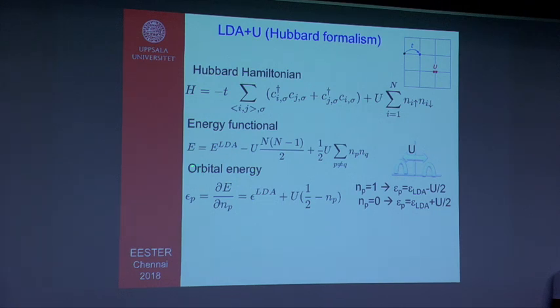And if you calculate the orbital energy, which is the derivative of the total energy with respect to the orbital occupation, you will see that it looks like this. It directly comes from here. Now if you put n, this occupation, equal to 1, then you see that the orbital energy comes out as epsilon LDA minus U over 2. And if you put it 0 in this expression, it comes out epsilon LDA plus U over 2.